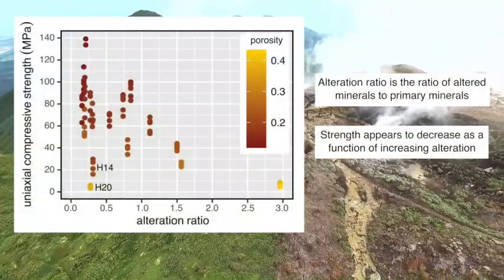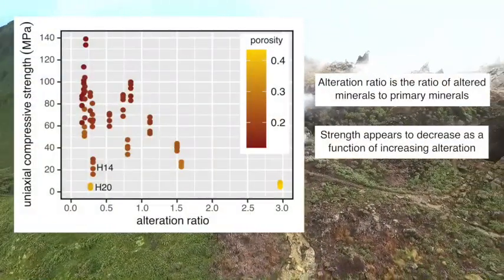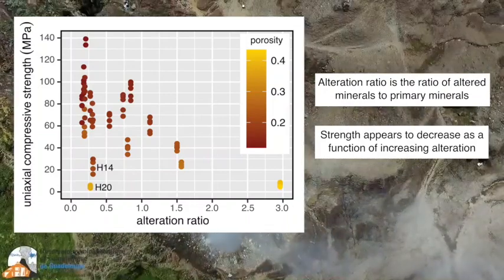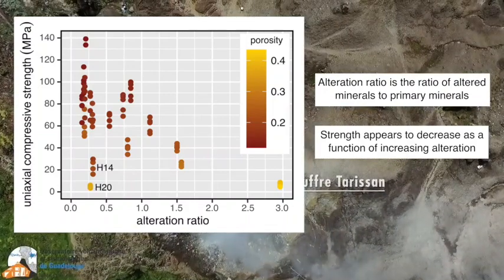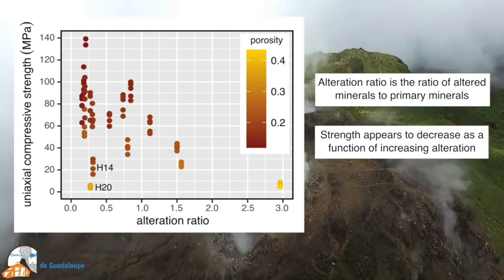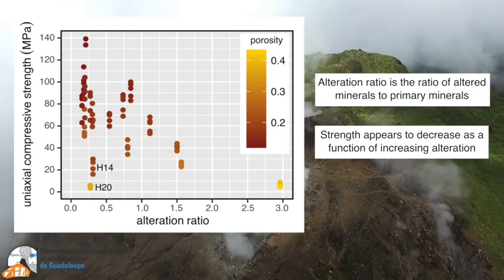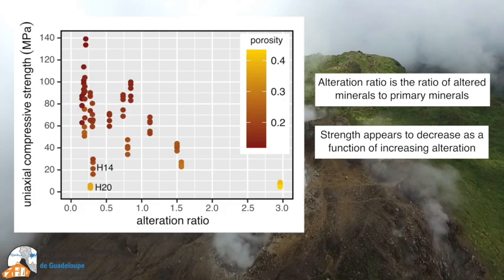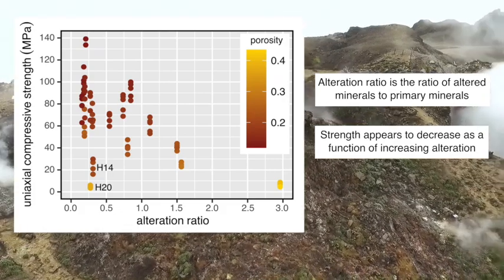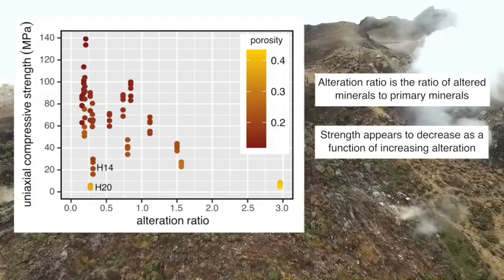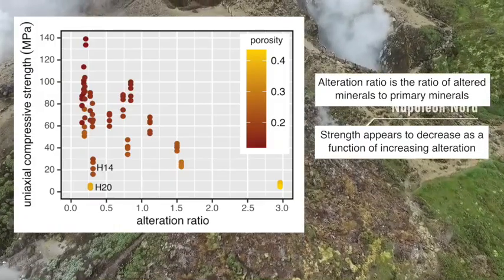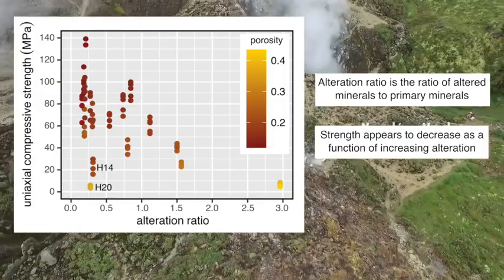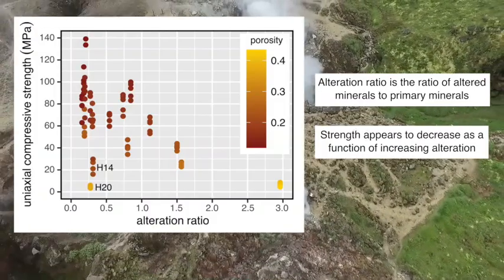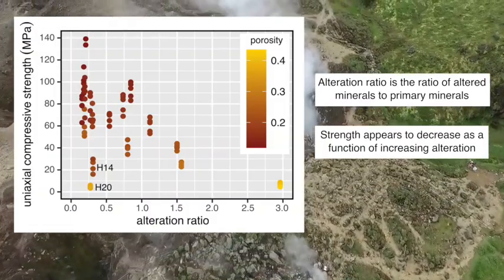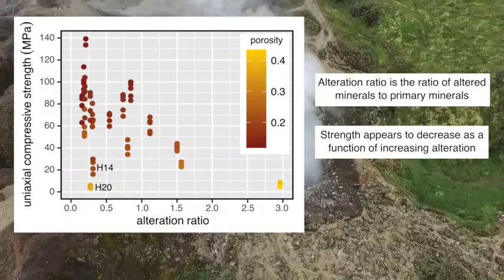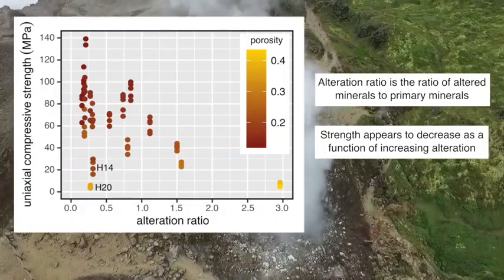Important to this study is whether alteration reduces the strength of andesites forming the dome at La Soufrière de Guadeloupe. The graph here shows uniaxial compressive strength as a function of alteration ratio, the ratio of altered to primary minerals in each block as exposed by the X-ray powder diffraction analysis. The porosity of each sample is indicated by the color scale, where yellow represents high porosity and red represents low porosity. These data show that strength decreases as a function of hydrothermal alteration.